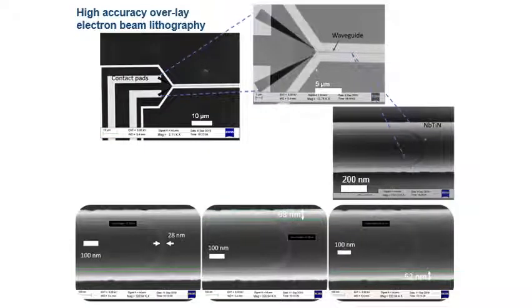Our next process I want to talk about demonstrates the overlay capability of our E-beam lithography system. So this is a 3-layer lithography process. The first layer are these contact pads, which are titanium on gold, done by liftoff of single layer PMMA. The next layer aligned with these pads is what we call a photonic layer, which is shown here, these trenches here. And once I zoom in, you can see these trenches.